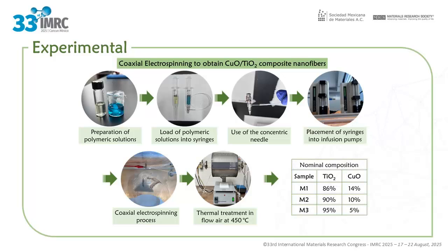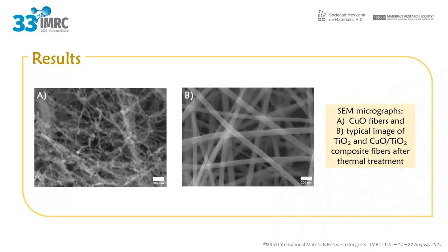For this work, 5 types of samples were synthesized: pure copper oxide, pure titanium oxide, and 3 coaxial nanofibers labeled M1, M2, and M3. In the latter, the external flow was kept constant at 0.3 milliliters per hour, while the internal flow was varied for each case: 0.3 milliliters per hour for sample M1, 0.2 milliliters per hour for sample M2, and 0.1 milliliters per hour for sample M3. Based on these synthesis conditions, the expected nominal composition of each oxide in the composite nanofibers was calculated, as shown in the table. We used scanning electron microscopy to analyze the morphology of the samples.